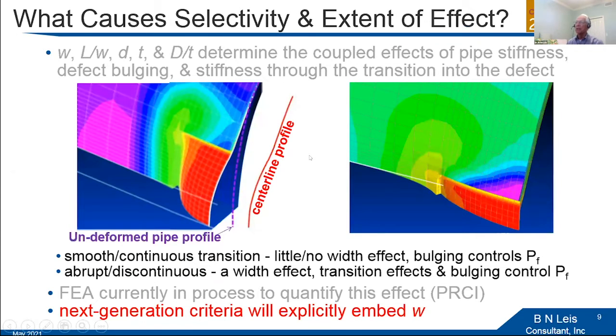So width can be a very complicating factor, and unraveling why it's a complicating factor turns out to be relatively simple if we contrast these two scenarios, the wide and deep versus the wide and shallow. You see here that there's a relatively gradual transition through the full wall into the part wall of the pipe. Whereas here you see a very significant transition, a very, very sharp change across that interface, and it's coupling bending and membrane tension here, where it's largely membrane tension here. And that's why width is a factor. Historically, we've ignored it, but as you can see, width was a significant influence, and next generation criteria will explicitly embed width effects as we move forward.